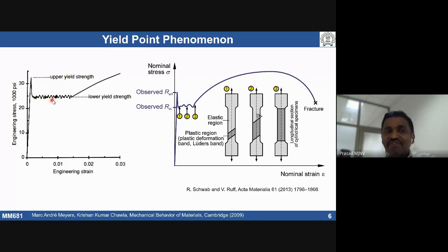The serrations you're seeing are basically a result of Lüders bands, depending on how many bands are forming. If it is only one band, we see a very nice line. But if multiple bands are coming from both sides, then we see these serrations forming in the material.